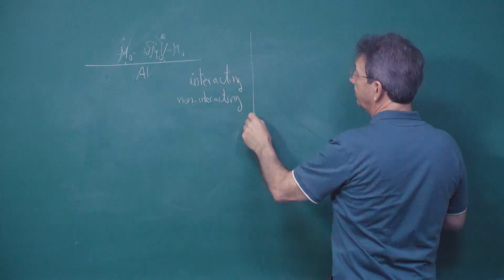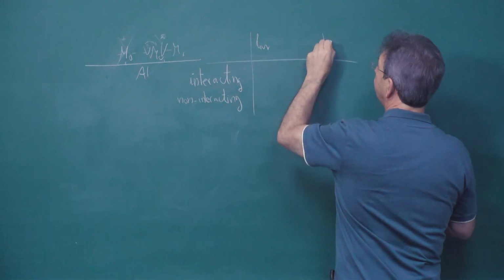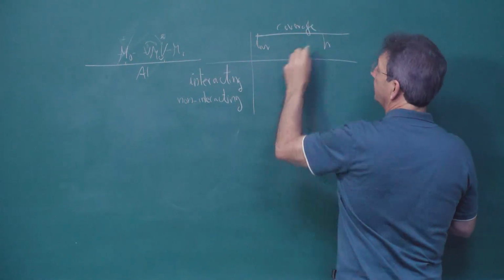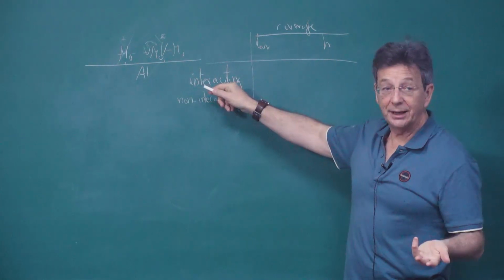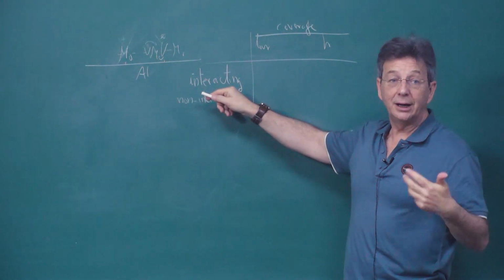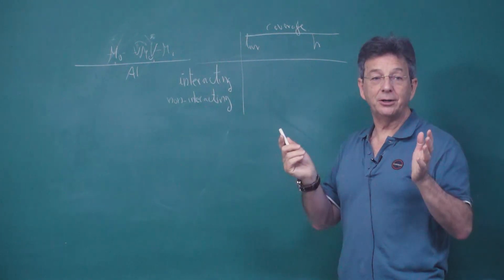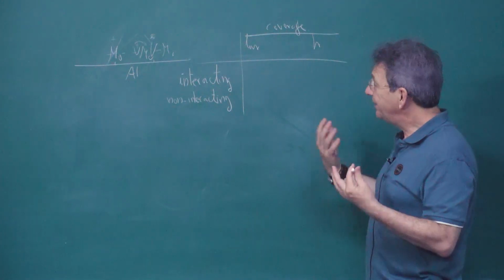Okay, basically let's say like that. This is like low and high coverage. If they are interacting elements like for instance vanadium or molybdenum and sodium, like we saw on the earlier days, they immediately form some kind of alkali vanadates or alkali molybdates. So they do form compounds.